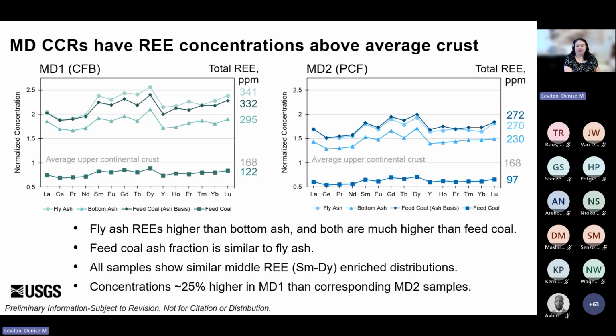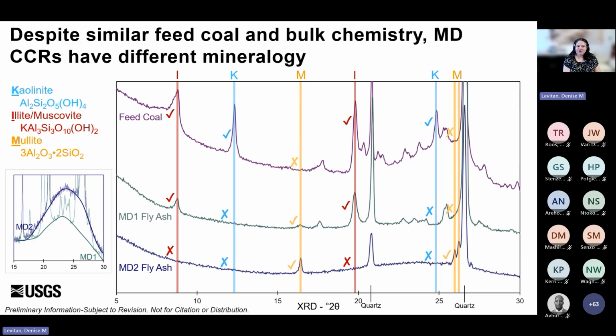Like the overall bulk element, major element concentrations, they're similar between MD1 and MD2, and they're similar, at least on an ash basis, between the feed coals and the ash or the CCR. So we've seen that the chemical composition is similar, but now we're going to look at the mineralogy. So this plot here shows X-ray diffractograms for the feed coal, the top in purple. It's basically the same, at least visually here, for both MD1 and MD2. So I've just shown one line. And then with MD1 fly ash in green in the middle, MD2 fly ash in dark blue on the bottom.